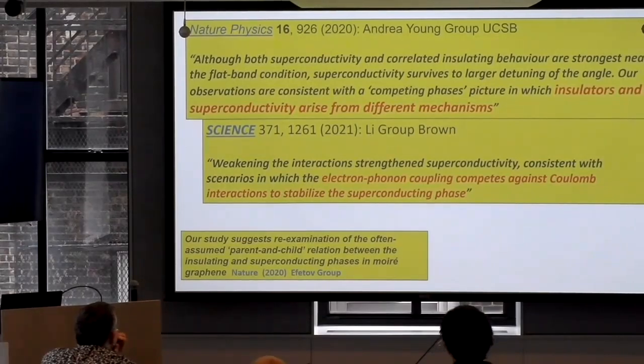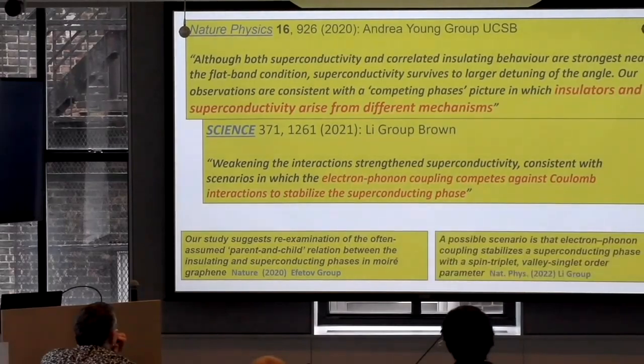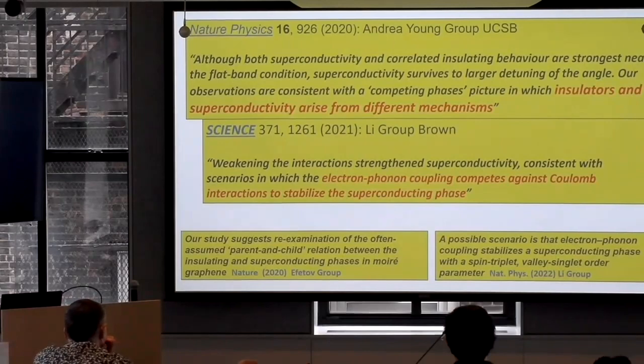Okay. Now, all these things came 2 years after we had already proposed superconductivity from phonons. So it's not like these papers motivated us. Nature Physics says a possible scenario is that electron phonon coupling stabilizes the superconducting phase with a spin triplet, valley singlet order parameter. This is what we said could happen. People originally thought you cannot get triplet superconductivity in the spin channel from electron phonon, but here you can. So our paper was posted long before.